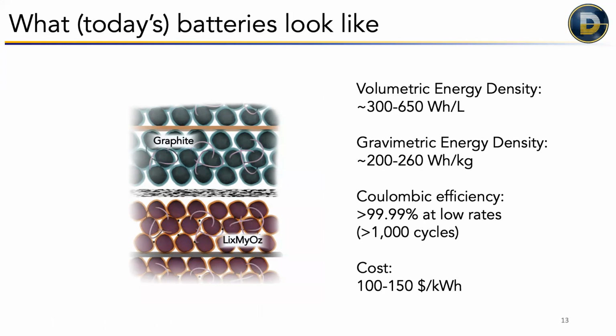One of the biggest reasons we really like lithium ion, beyond the energy density, is the fact that it can be cycled extremely efficiently. And this isn't energy efficiency, this is Coulombic efficiency. So if you send 10,000 lithium ions from one side of the battery to the other, you can get 9,999 of them back in most cases, which means that you can cycle them back and forth well over 1,000 times, sometimes up to 5,000 times.